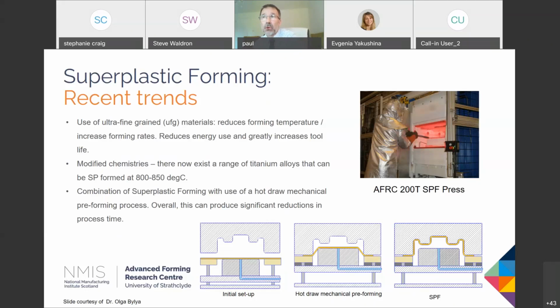And why would you bother doing that? Well, it gives you an opportunity, if you're interested in SPF of titanium, of either reducing the forming temperature or increasing the forming rate. These are both good things, of course, but most manufacturers would tend to want to reduce the forming temperature, because by reducing the forming temperature even by 50 degrees C, or better 100 degrees C, which is what these ultrafine grain materials do for you, you can greatly improve your tool life. So if you're on a big production run, you don't need to take the tools out, clean them up, and then put them all back in again on such a regular basis. So that's a big bonus.